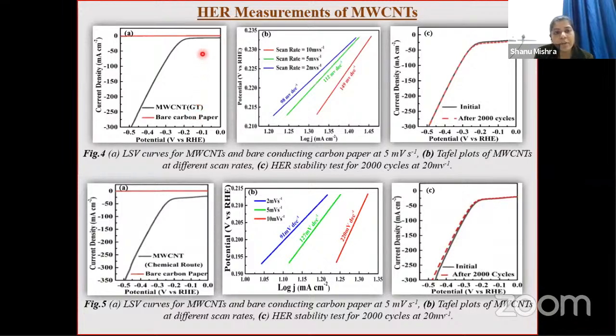The linear sweep voltammetric curve suggests that bare carbon paper has no activity towards the HER, while the MWCNT has a much higher current density. For any catalyst, if we are saying that it's a good HER catalyst, it's important that it possesses a lower Tafel slope.